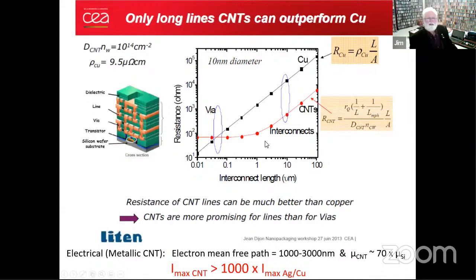But carbon nanotubes are not the cure-all for everything that people seemed to think at one point. So here is the statement that only long CNT lines can outperform copper. That's because at very short distances, copper is actually a lower resistance effectively. The resistance of the carbon nanotube is independent of length until it gets to a certain point, and then you have secondary effects coming in.